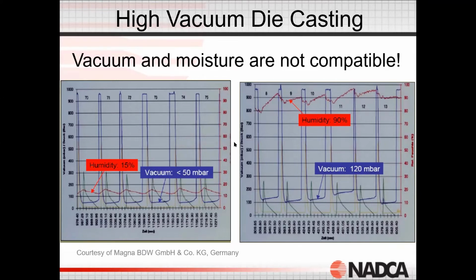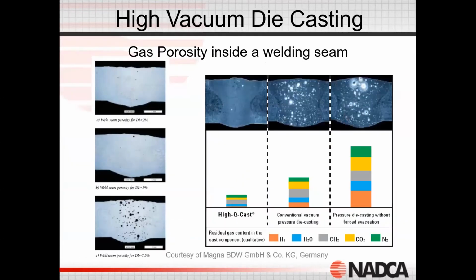So if we're measuring humidity, we can see the difference of 15% to 90%. We're now producing a casting that may have detrimental effects or excessive porosity, giving us blisters and defects. So we can see that this low gas porosity is very key in making good weldable seams and in our joining operations. So we're just showing the difference between different types of vacuum systems. This is a high vacuum system. This is a conventional vacuum system, and this is without any vacuum. We can not only see the type of air that's entrained in the casting, you can see the amount of air in these x-rays. And then these type of conditions are going to give us a good weld seam. So this is actually the weld seam we're looking at, from the different processes.